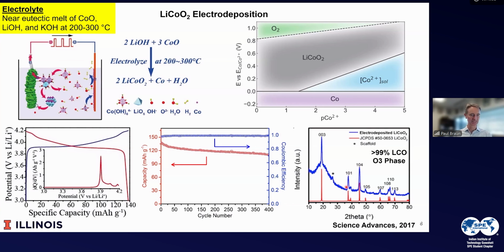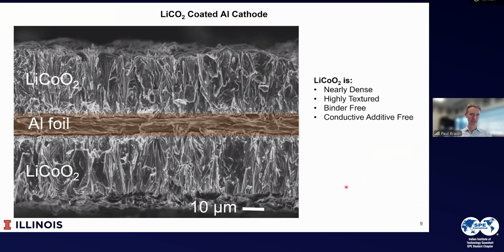And this is just a larger view of this same lithium cobalt oxide coated cathode. What you can see here is that the lithium cobalt oxide is nearly dense, highly textured, binder free, and conductive additive free. So this is a material that eliminates some of that dead or inactive mass that I was discussing. As you can also see, the grains are highly columnar, and these highly columnar grains provide fast pathways for electron transport and for ion transport.